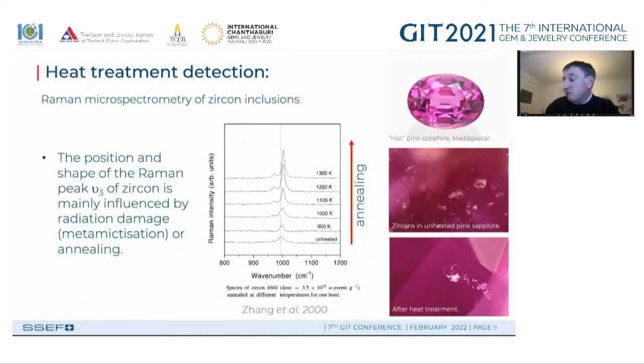Another way to work with such a stone is to work on inclusions. And here we have a figure showing the change in the Raman spectrum on zircons related to a heat treatment, starting from a very metamict state where the peak is very broad, and due to the heat treatment, this peak becomes more and more narrow. Now, this is a very useful criterion and can be used for corundum which is heat treated at rather high temperatures, let's say 1,200, 1,400, and even more.